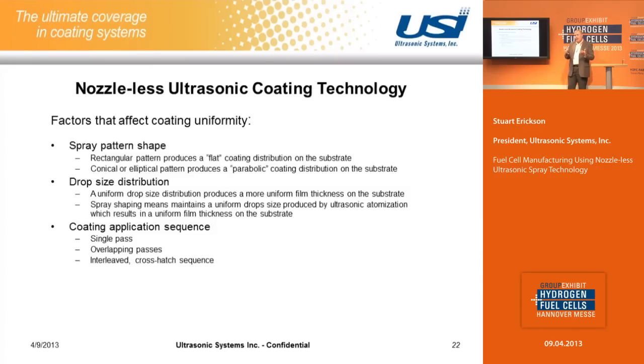Since our ultrasonic head can generate a very uniform drop distribution, as long as we can shape the spray and maintain that drop distribution, we can also increase the uniformity of the coating on the substrate. And this really matters when you're trying to put down very thin coatings.